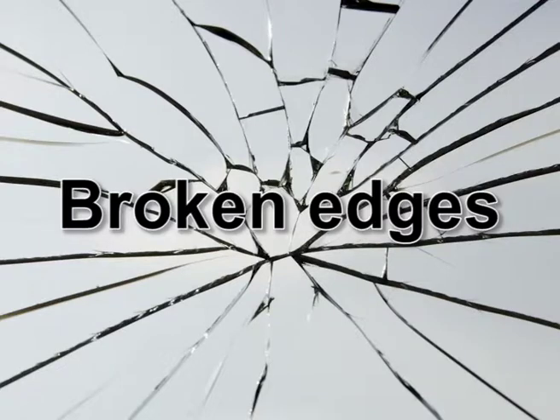Then come the broken edges. When there is a cut on the surface placed under tension, the glass may not break squarely across. When a piece of glass is broken by bending from a larger piece, the sharp edge remaining on the larger piece will probably be on the side to which the force has been applied.